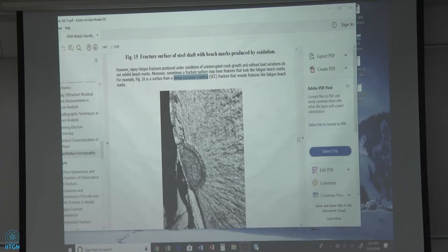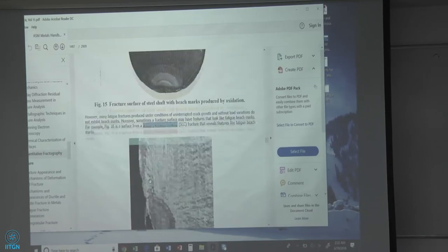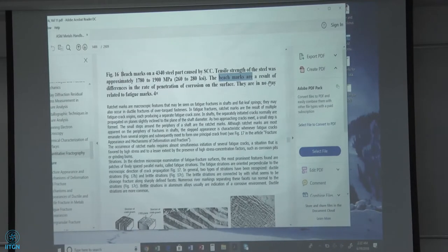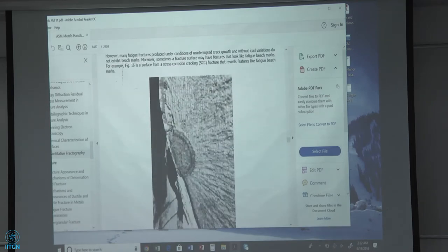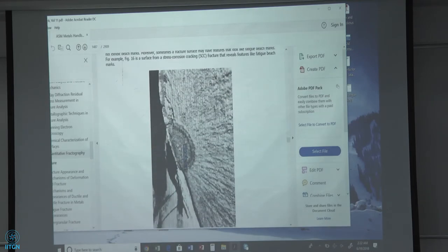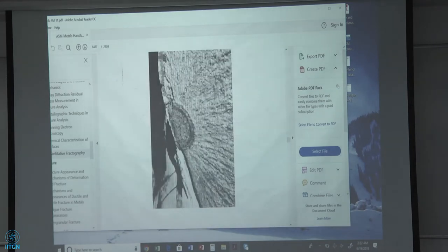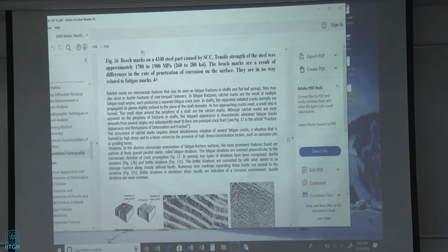So I got all these things in for you. Goswami, not Majumdar, Goswami, he did some low cycle fatigue, these kinds of dwell fatigue tests, right? So basically you're holding it here. Instead of holding it at constant load, this is a constant load, constant stress, constant K test. Here it's a low cycle fatigue test, and you're holding it at a constant strain. And the load, okay? You're holding it at a constant strain.